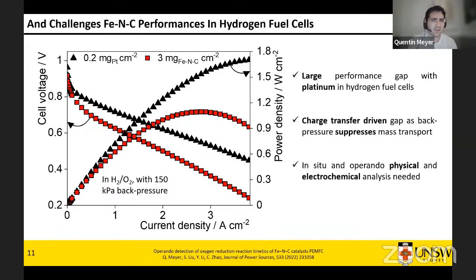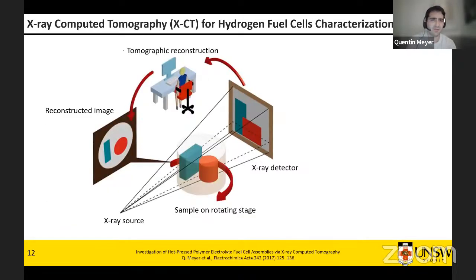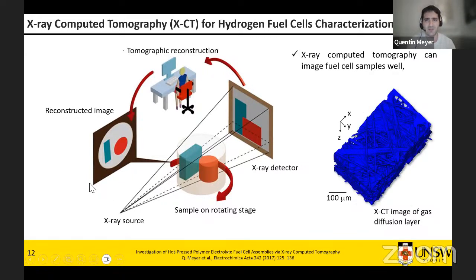And we know that we shouldn't have too much gas transfer problem because we apply a large back pressure. And so what's happening is there's probably some very large charge transfer driven gap. And we want to know why there is such a big difference. So the first technique we're going to use is called X-ray imaging or X-ray tomography. X-ray tomography is basically done by having an X-ray source and a small sample that we image at one angle, then you rotate it, and you take another image, and then what you end up with is a full tomographic reconstruction or full 3D image of your cell.